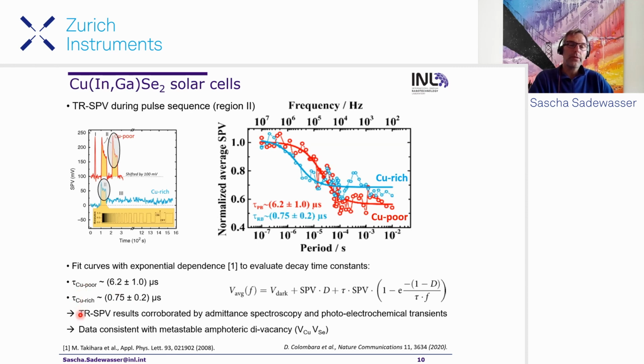So there were lots of other techniques, also transient techniques, applied to these materials: admittance spectroscopy, photoelectrochemical transients, and so on. And all our data is consistent with the metastable amphoteric di-vacancy defect. So essentially what happens below the surface, due to this etching of the copper selenides, the copper from the bulk or from the below surface region starts moving to the surface again and leaves behind copper vacancies that then form this di-vacancy complex with selenium vacancies in the material. And this leads to these metastable effects.